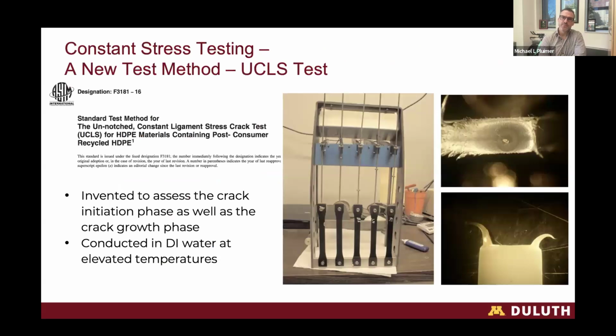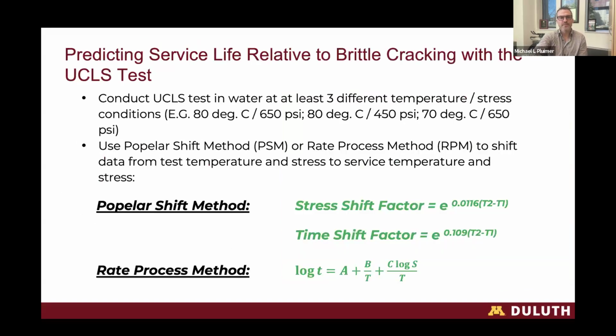So to do this, we actually had to invent a new test method called the unnotched constant ligament stress test. This is testing materials for their stress crack resistance relative to the different contaminants and different materials that might be in that material. For example, for a virgin material, there might not be a real likelihood that you're going to have a contaminant, but that likelihood could be increased if we're incorporating recycled materials. So we invented a new test method to test the effects of those contaminants on the stress cracking mechanism, and then we tied that test method to service life.